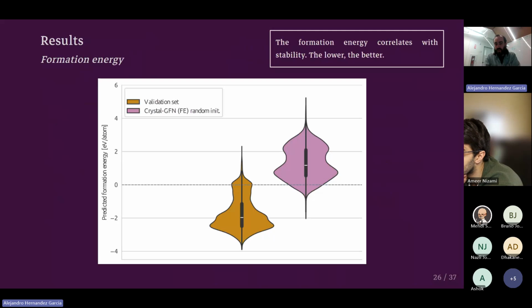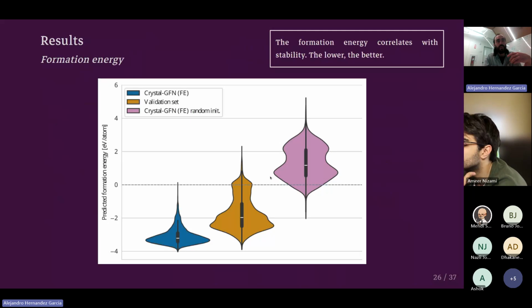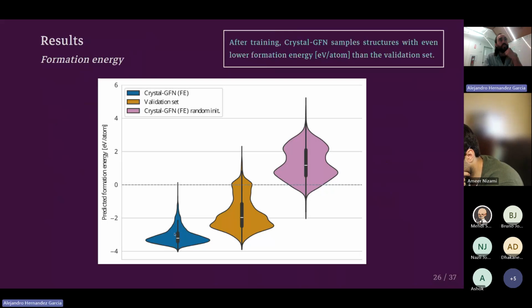If we take a Crystal GFlowNet, as I explained before, and we let it generate crystals before we train it, so at random initialization, the distribution we get is this one here in pink. It's a distribution that is mostly on the positive part of the formation energy. So this is bad, let's say. This is not good because the majority of the generated crystals are going to be unstable. But once we train the Crystal GFlowNet, we get a distribution that has even lower formation energy than the validation set. So that's good news. It means that it has learned to generate crystals with low predicted formation energy, predicted by the proxy model that we use.